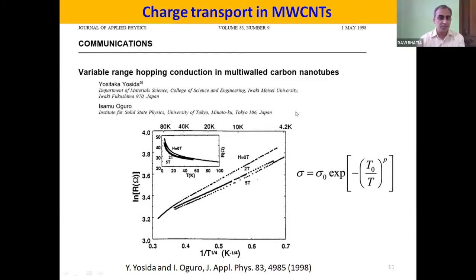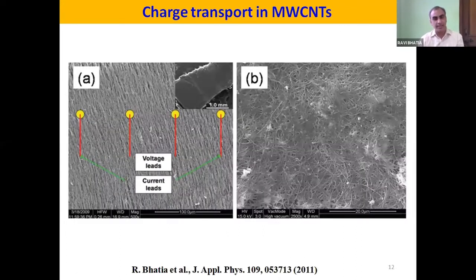So this does not provide us the true picture of the electronic properties of carbon nanotubes, because we have heard many a time that multi-wall carbon nanotube should represent a metallic transport rather than a VRH transport. So this paper was the basis of the next work which we carried out. We prepared two types of samples. One was an aligned sample of carbon nanotubes, and the other is a randomized sample, just to look at the inter-tube transport within the sample. So whether the alignment or the randomization really affects the transport properties or not?